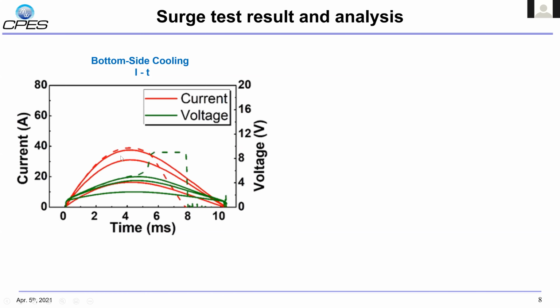Here is the surge test result and analysis. For the bottom side cooling, we can see that the peak surge current that the gallium oxide Schottky barrier diodes can endure is about 39 amp. And here's the burning point. We can see that it's an open circuit. There's no current. It's an open circuit after the burning point, which indicates the wire bond burnt.